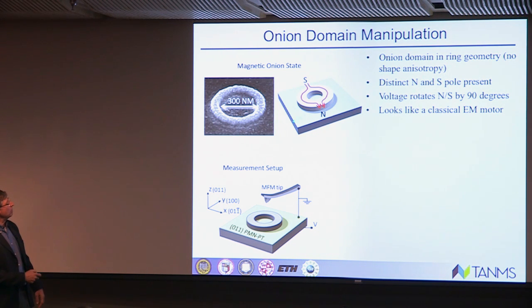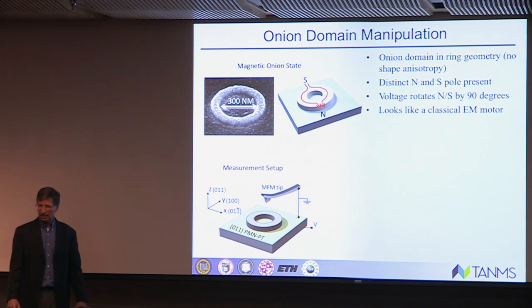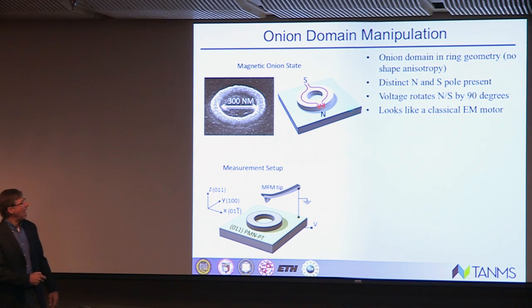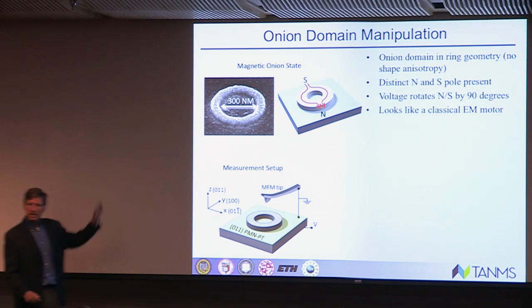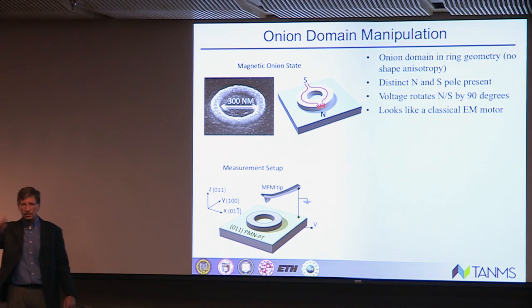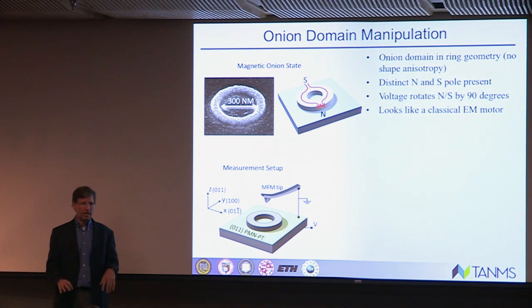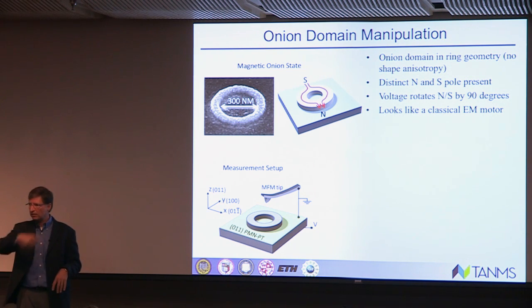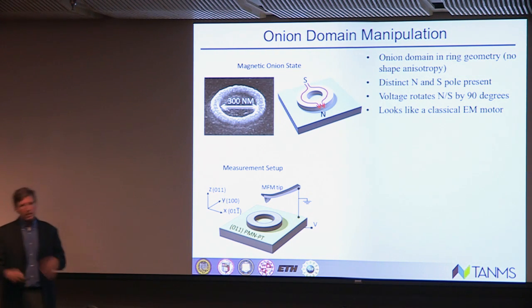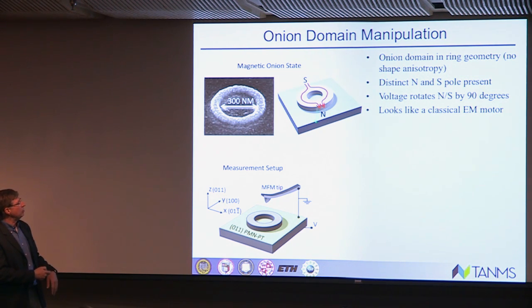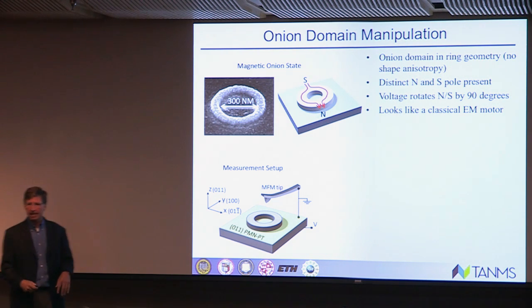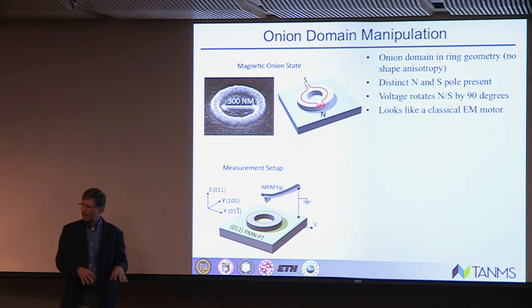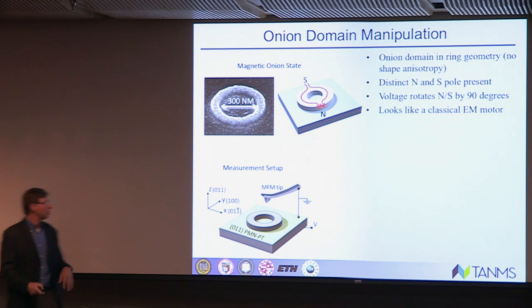And if you look at the structure, what's really nice about it is you can create an onion state embedded in that, where you have a north and a south pole. Now, the reason we like this ring structure is there's no shape anisotropy. So if you look at it, it's symmetric as you walk around the ring. So what that implies is that you should be able to have an easy time reorganizing those spin states. And that was our premise.